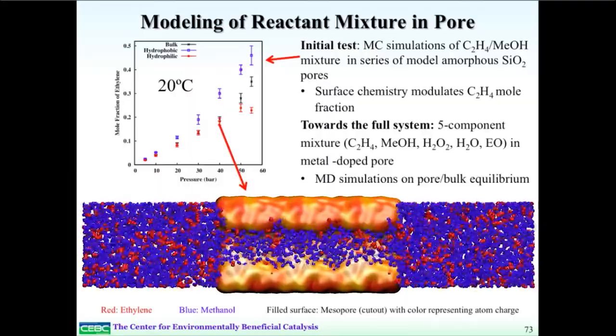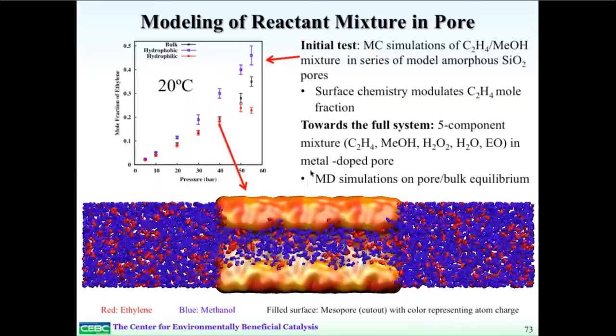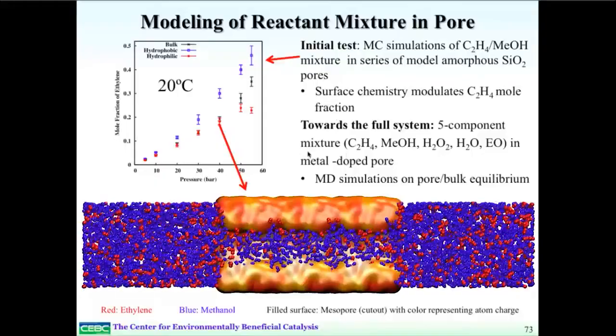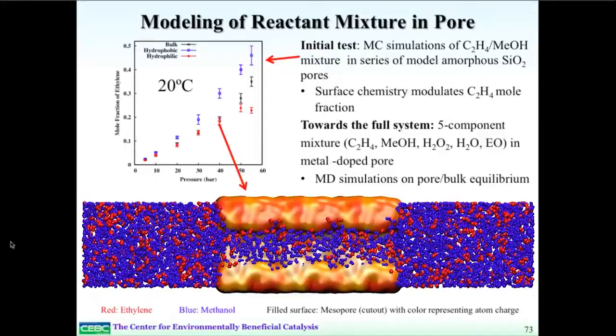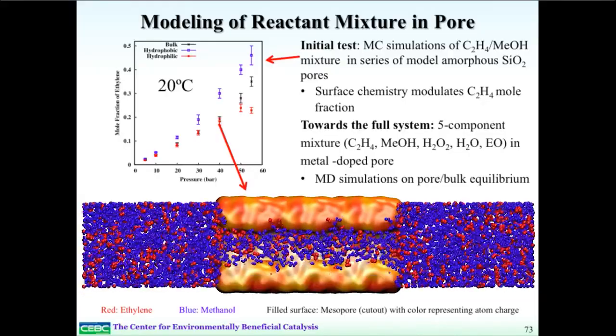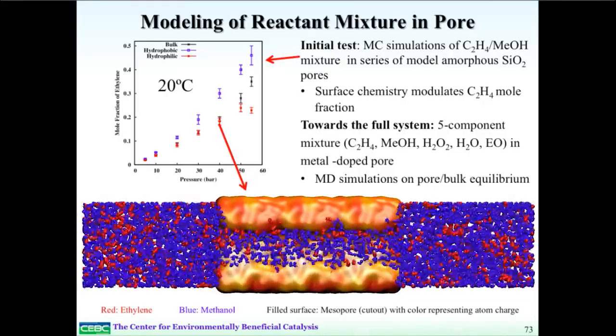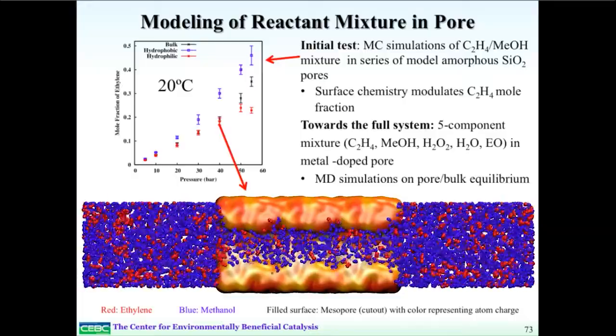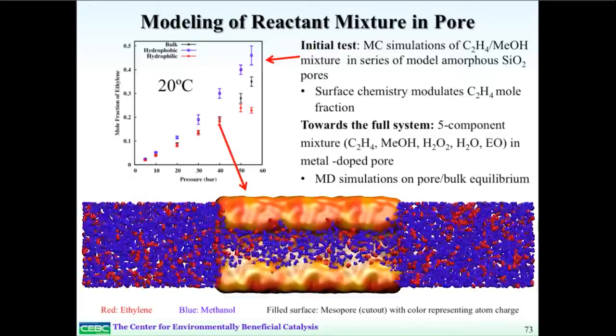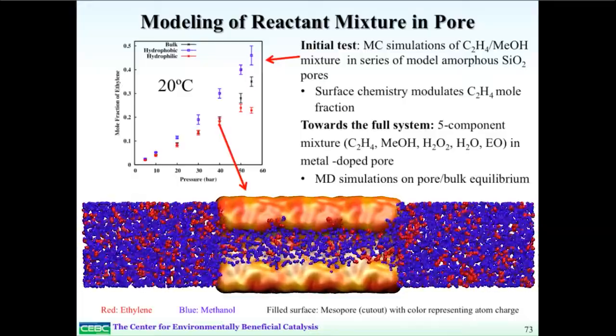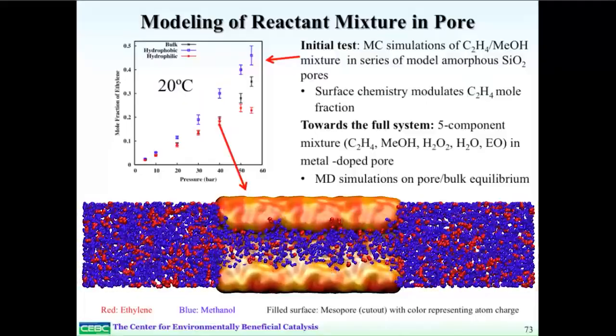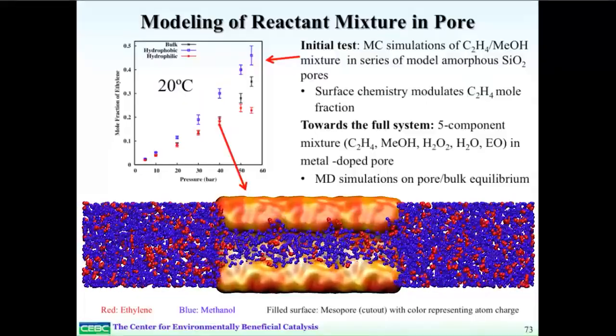We can also get towards the full system by looking at a full 5-component mixture. And this is a case of looking at some MD simulations on the pore bulk systems. What you actually see is a mixture of ethylene and methanol. This is at this 40 bar pressure for the hydrophilic pore. And we can get a good picture of what's going on inside the pore on a very detailed molecular level to help the reaction engineers understand how to create models for this.